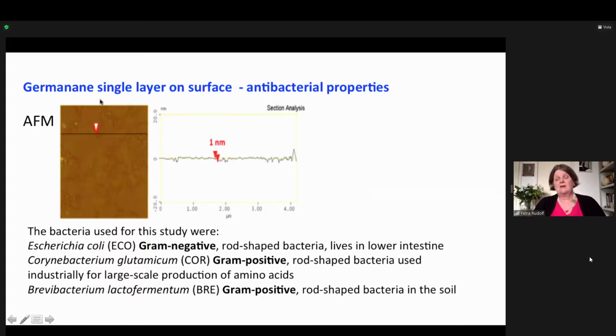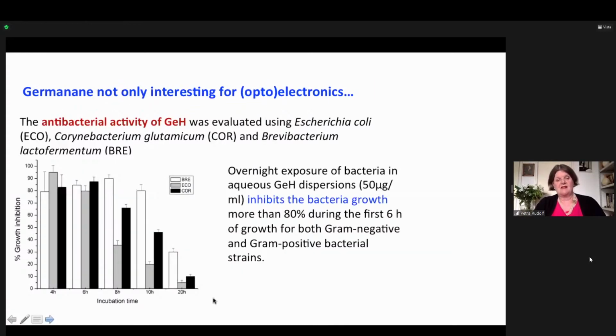Now, what we tested with this was also completely different properties, namely antibacterial properties. And what we used for this study were both gram-negative and gram-positive bacteria. And of course, I'm a physicist, so this was not done in my lab, but we collaborated with people who know how to do this, in particular the Stamatis group at the University in Ioannina. And what they found is that overnight exposure inhibits bacteria growth for more than 80% in the first 6 hours for both gram-positive and gram-negative strains.